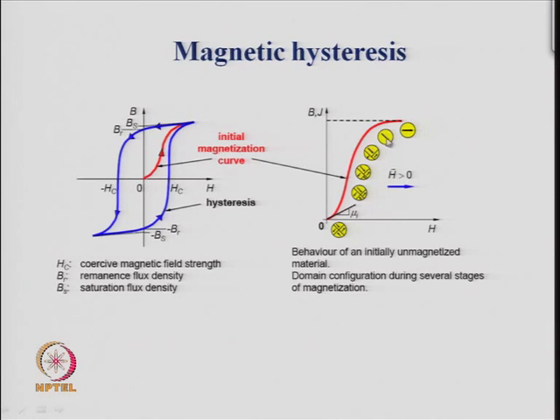You can see a very large vector in one direction, but the magnetic field is in this direction. So, this vector is not yet aligned with this direction, but all the vectors within different domains have now become one and you have one magnetic domain. So, this is a single domain particle, though the magnetic vector is not aligned with the magnetic field. Now, if you increase the field further, then the direction of this vector also becomes aligned with the magnetic field. So, that is the final stage, that is when all the small domains have converted to one domain and the vector in that domain has aligned with the applied magnetic field, and that is the maximum magnetization you get.